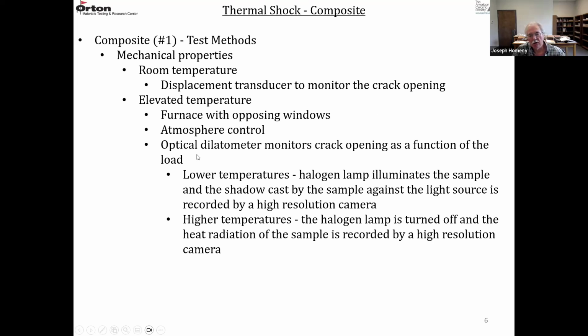And then you can get that horizontal displacement from an optical dilatometer. So that can monitor the crack opening as you load the material. So in this work at the lower temperatures, they use the halogen lamp that illuminates the sample and it casts a shadow. The sample casts a shadow against the light source, and they have a high resolution camera that records the movement of the shadow. Then when you go to higher temperatures where there's enough radiation to see the sample, you don't need the halogen lamp, and you use the radiation of the sample to record the displacement again with a high resolution camera.